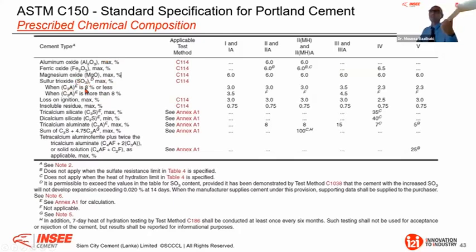After you have SO3, depending if you have less than 8% or more than 8%. You see, when more than 8% here, you cannot apply it for moderate sulfate and moderate heat, because this is a product that develops heat, and the problem with sulfate is from the C3A. But when it's less than 8%, you have to use average 3% on SO3, 3.5 when it is for type 3, and 2.3 for type 4 and type 5. Here again, there is a performance-based test saying that if you perform a test on heat or on sulfate and you pass the performance test, you can be above 8%. That is really a big move that those standards have made in the last decades.